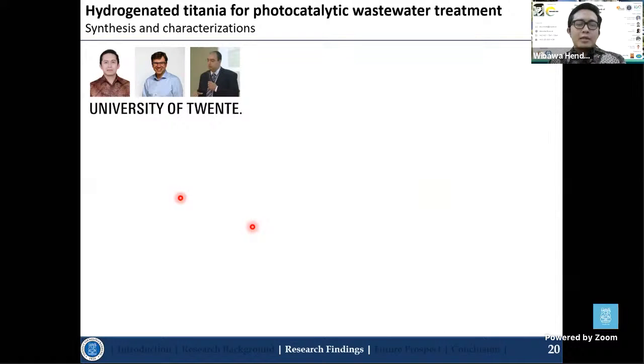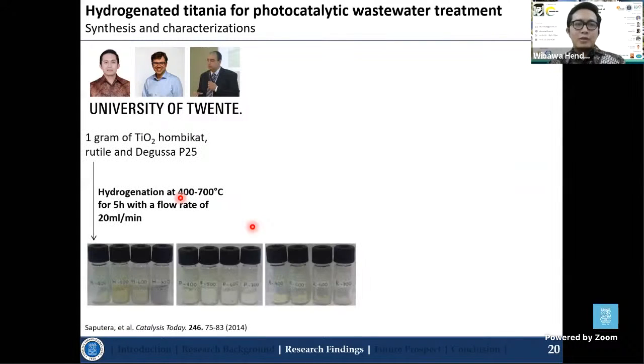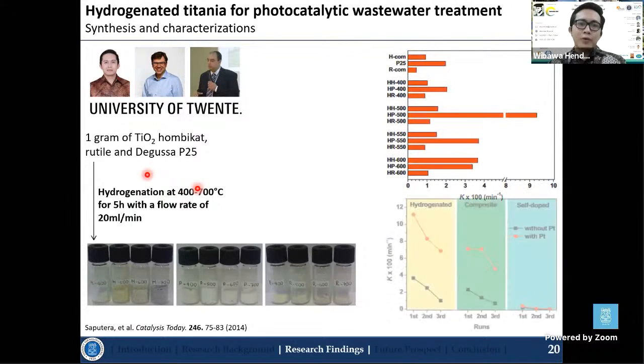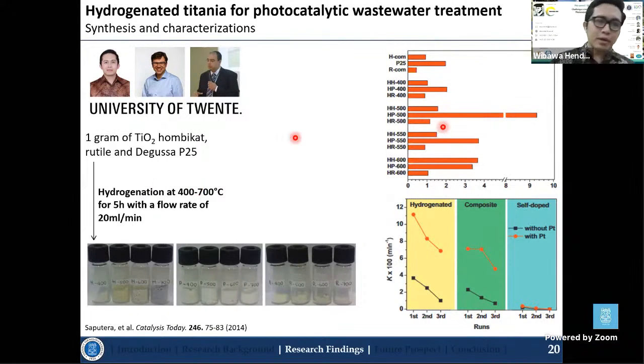So the second method is about hydrogenation of the titania. It's almost the same as the previous one, but this one uses hydrogenation, or purging the samples with hydrogen. So it can be seen here that the catalyst with the P25 Degussa hydrogenated at 500 degrees C gives the best performance compared with other samples.